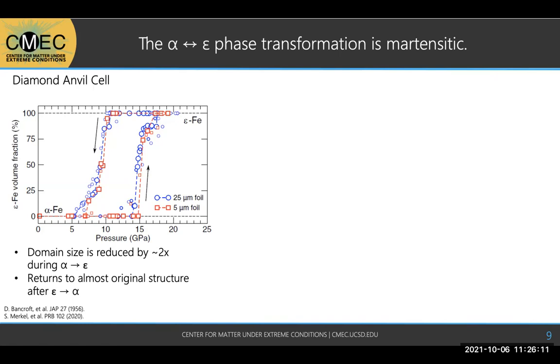And what's also important in these experiments is that during compression, they saw that the grain size or the domain size was reduced, and then during decompression, it actually reverted to something similar to the original structure. And I say this is important because in material science, grains are one of the biggest contributors to strength, where smaller grains generally mean that the material is stronger.